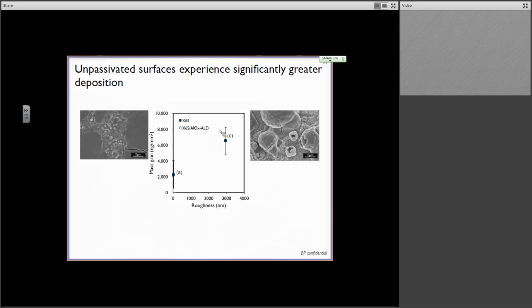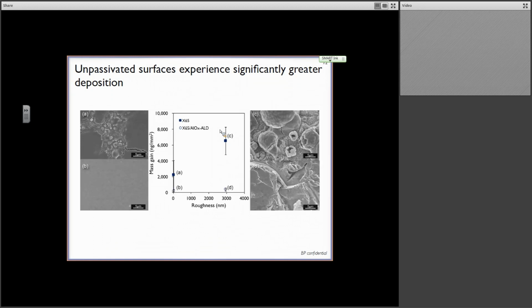But before we do that, I want to just give you some reference: here is what happens if we put that aluminum back on the surface. And that corresponds to these data points down here. So these are still the same steel surface that we're working with in the top 2 data points, except obviously there's substantially less fouling. And if we actually go searching for deposits on these surfaces, I will forgive you if in B you can't see anything, it's just a gray box, because effectively it is a gray box. There's something on the surface, but not much.